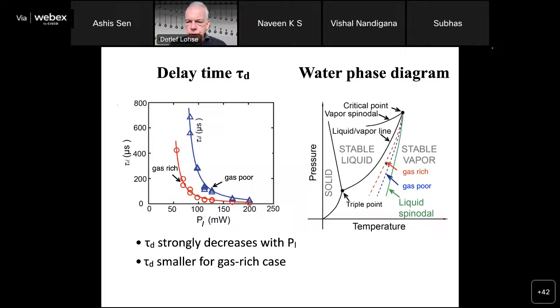This, in fact, happens earlier for the gas-rich case, because for the gas-rich case you have more little crevices and little gas bubbles around. So you nucleate the vapor bubble earlier because you have more nuclei. For the gas-poor case, you can superheat in a much stronger way. So this nucleation temperature, of course, does not depend on the laser power, but this delay time does depend on the laser power, because of what I explained about the number of nuclei which are around, and therefore it strongly goes down.